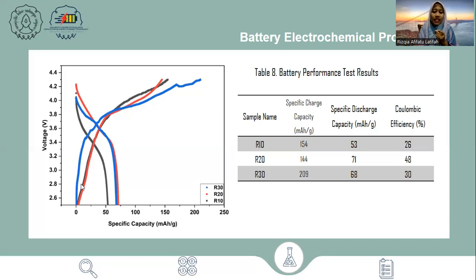Coulombic efficiency is still low because of the presence of a solid electrolyte interface layer in the first cycle of the charging discharging process. These layers can reduce the active electrode area, so that in the next discharge process, the lithium ions returning to the cathode structure are fewer than the number leaving the cathode. So the Coulombic efficiency is less than 100%.